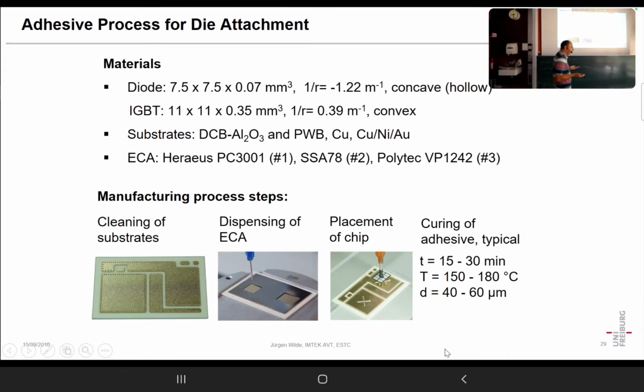Also in such adhesive bonding, it is really important that we do not get porosity or such a thing in the interconnection. Again, too many pores would lead to high thermal resistance, and that again would lead to overheating. That's important because in big chips, we normally have high dissipated power. That can be both in processors, like in your PC, and also in power chips. It can be, let's say, in the range of 20 to 100 watt, just heating in that square centimeter. And you must get rid of that heat here.